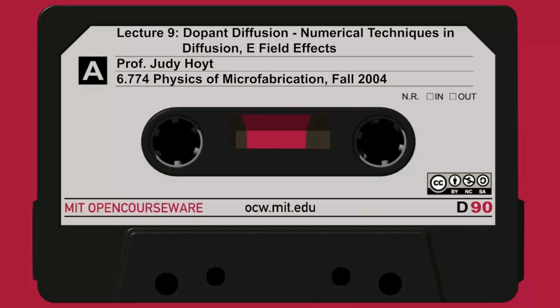But because of the Einstein relation, when we're talking about the diffusion of carriers like electrons and holes, we know that their mobility is directly proportional to the diffusivity, and the proportionality constant is q over kT. So mu is equal to D times q over kT.